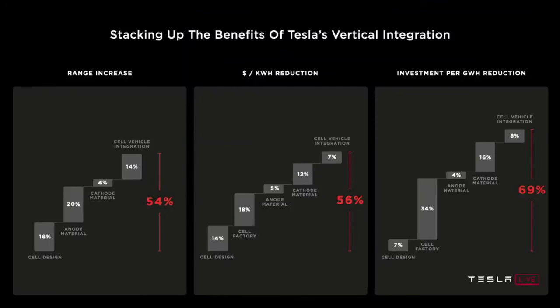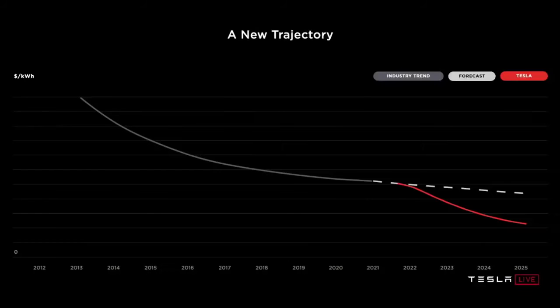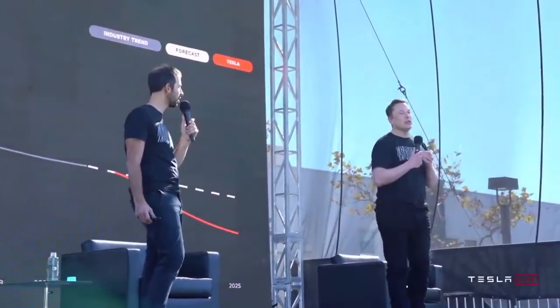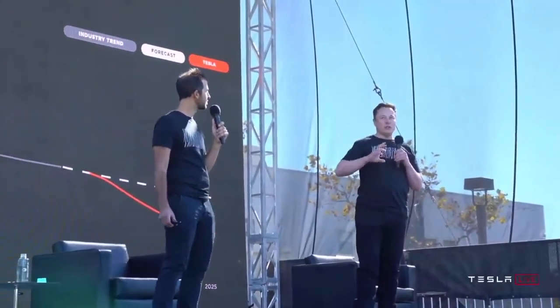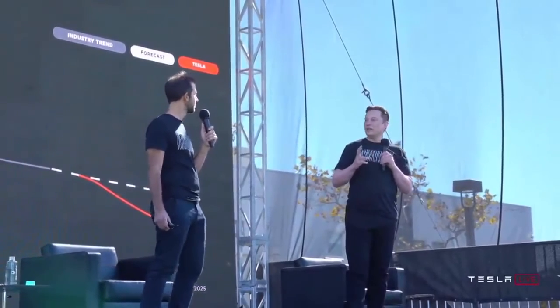Range increase, we're unlocking up to 54% increase in range for our vehicles and energy density for our energy products. 56% reduction in dollars per kilowatt hour at the battery pack level, and a 69% reduction in investment per gigawatt hour, which is the true enabler when we talk back about how do we achieve this scale problem here. What this enables us to do is achieve a new trajectory in the reduction of cell cost. And now, to be clear, it will take us probably a year to 18 months to start realizing these advantages, and to fully realize the advantages, it's about 3 years or thereabouts.